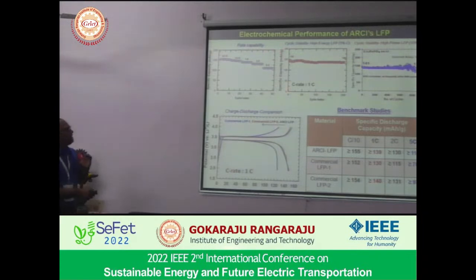And if you can see the cyclic stability, we are getting nearly 95% retention of capacity after 850 cycles. We have two materials: one is a high energy material where the carbon content is less, and another one is a high power material where the carbon content is 10 weight percentage. In both cases we obtained good cyclic stability.